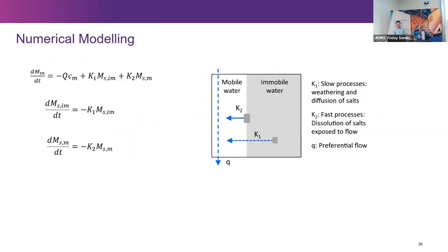So the next step, as I said, was to develop a simple numerical model using kinetic parameters. So fast and slow processes. For example, this is a simple mass flow model. It's not a mechanistic model such as HYDRUS. So this tells us how much salt will release over time from columns and IBCs, taking into account slow processes, K1, that is coupled with weathering and diffusion of salts, and fast processes, K2, dissolution of salts exposed to the flow.